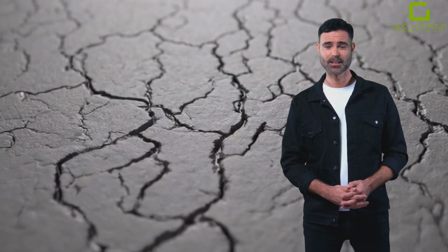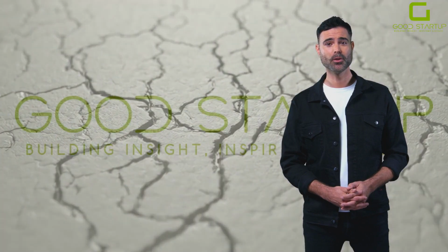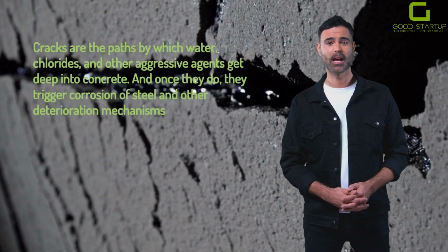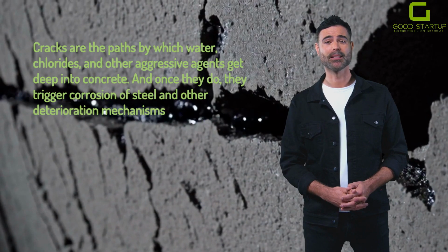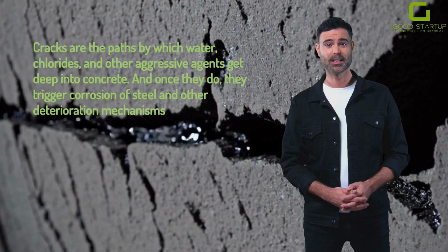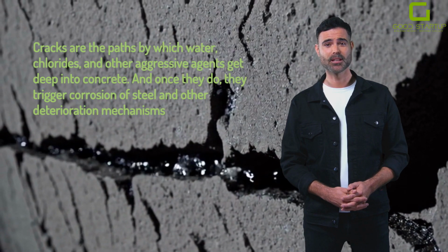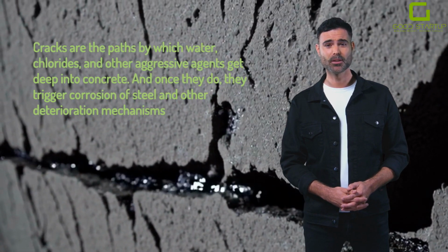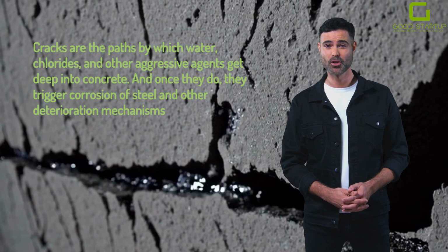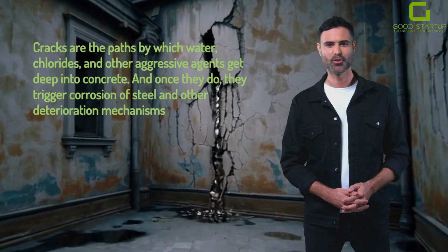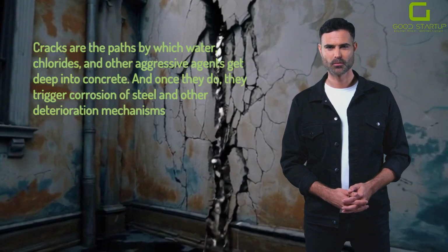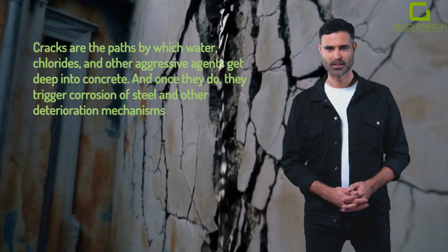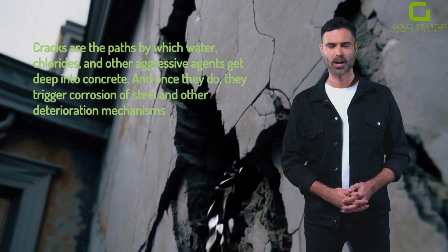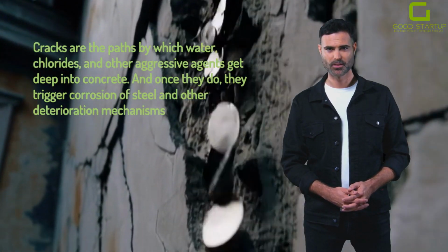Now, why do these hairline cracks matter for life cycle costs? Because cracks are the paths by which water, chlorides, and other aggressive agents get deep into concrete. And once they do, they trigger corrosion of steel and other deterioration mechanisms, which are the real budget killers for owners. A tiny 0.2 or 0.3 millimeters crack can allow water to reach the rebar, start rusting, and before long you have spalling concrete and costly repairs.